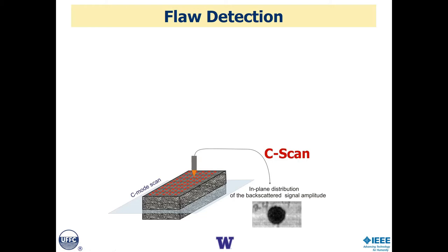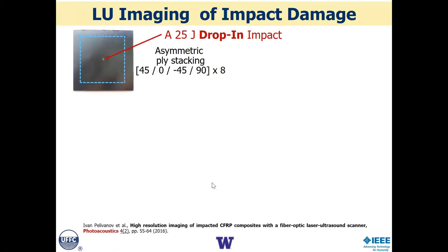So it's like you're peeling away layers of the material by looking through the movie. So here's a simple test that demonstrated the power of this approach. Here's a composite component that we got from our friends at Boeing. We drop a ball bearing on it according to their specifications, and you can see just a little dimpling of the surface.